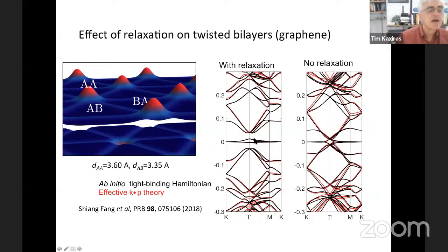So this is the band structure, electronic states. The vertical axis is energy of the electrons. The horizontal axis is momentum in reciprocal space. These are the high symmetry points in the reciprocal space, K, gamma, M, and K. So these are the bands now. And you see the flat bands, but only after you have taken into account the full relaxation of the atomic sites. And I'm showing you two sets of bands here.